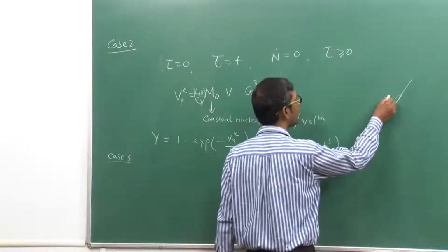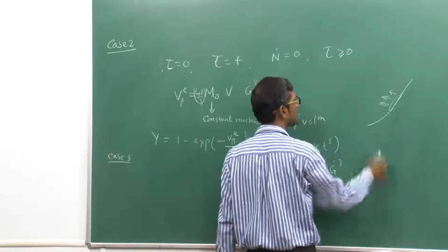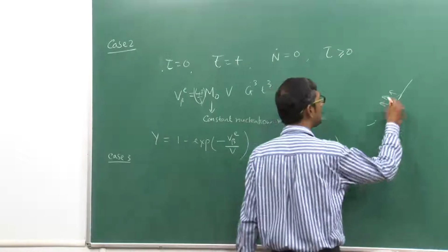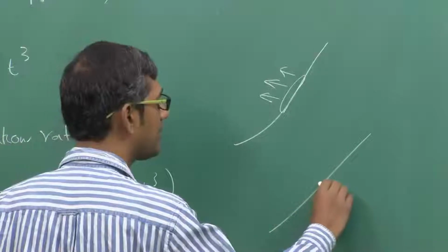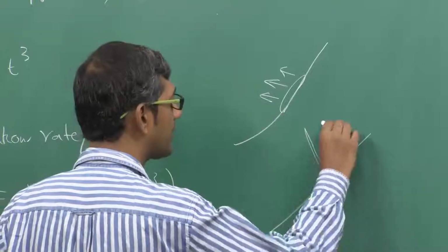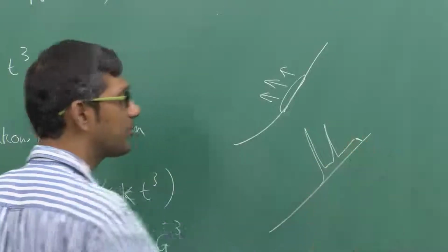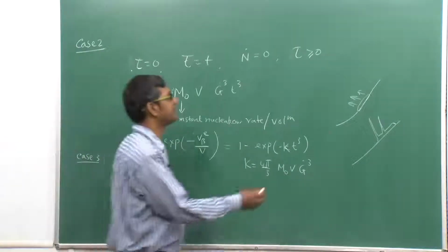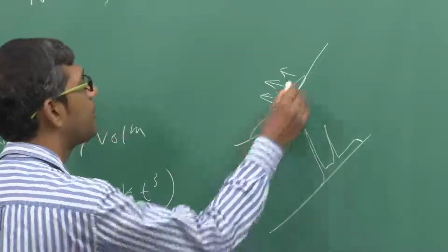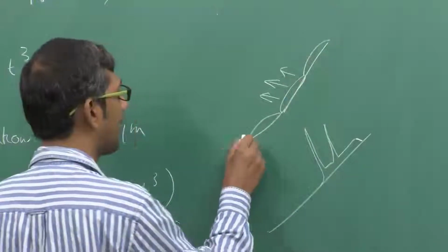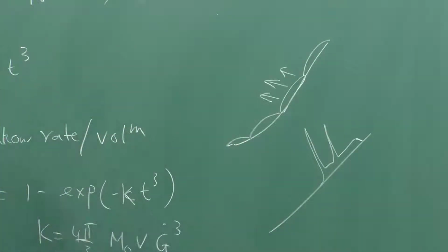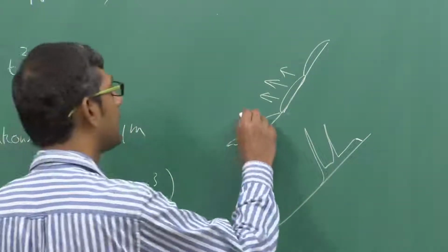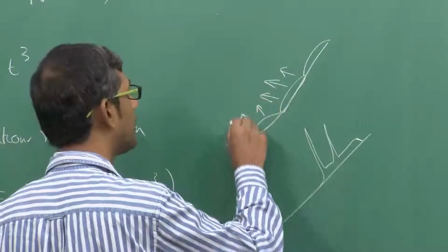So, this growth will happen perpendicular to the grain boundary. That is what you see in many cases, these things form Widmanstatten structures, we have seen in the case of steels also, and this is very common. Therefore, if this grain boundary is completely filled by these nuclei and no further nucleation is possible, the growth will only happen in the direction perpendicular to the grain boundary, correct.